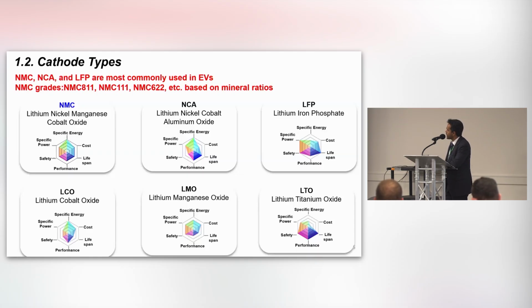The black mass, as I mentioned, comes from the lithium-ion battery. Based on the metallic composition, the cathode can be categorized into mainly 5 or 6 categories like this. But in this study, we use the NMC black mass that contains high lithium, nickel, manganese, cobalt oxide. Based on the critical mineral ratios, we can have lots of grades of NMC black mass.